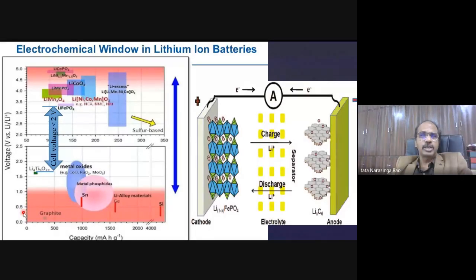But if you want fast charging, then you can use lithium titanate, Li4Ti5O12. You can see this is used instead of graphite, but they're compromising this much voltage. My voltage will be only 2 volts instead of 3.5 volts. But I am still in the safe region and I can do very fast charging. But I need more number of batteries because I only have 2 volts.